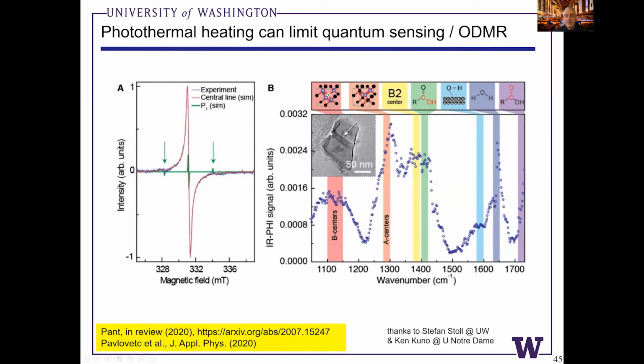So this is a TEM image of a diamond that we've been working with from Adamas, and these are really fantastic materials for doing ODMR spectroscopy. They have very bright NV centers, and we've been using these for ODMR measurements. But they're on the order of 100 nanometers, sort of milled from bulk HPHT materials.